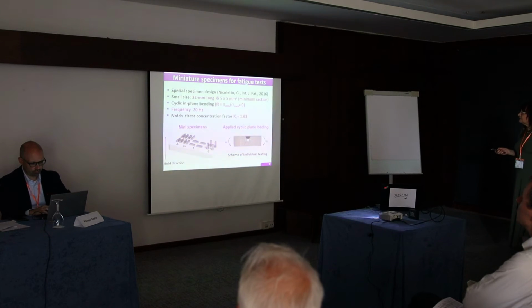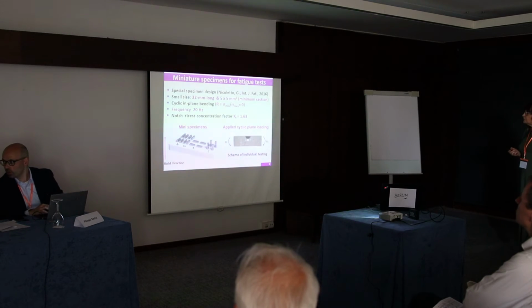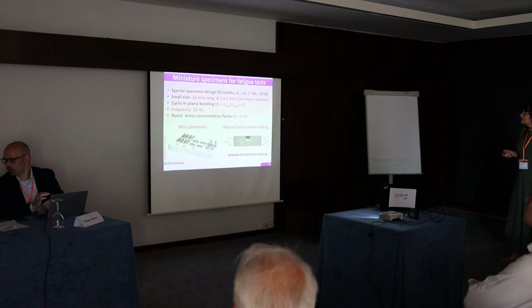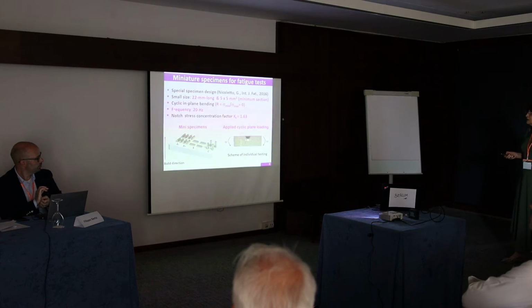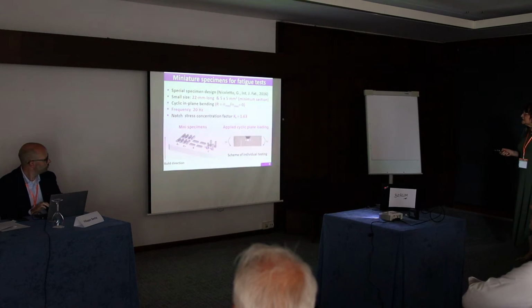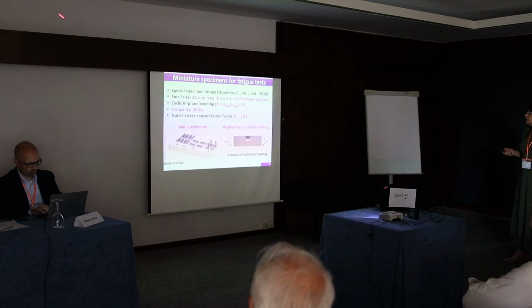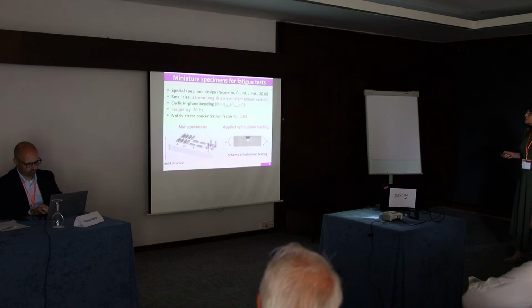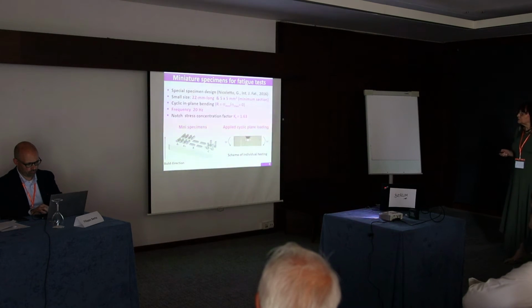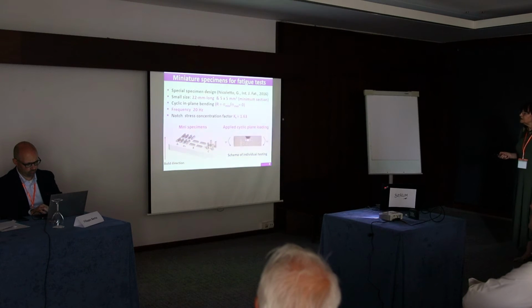Here we can see miniature specimens for fatigue tests. This is a special specimen design prepared by Professor Nicoletto from the University of Parma. The specimens are small, so here are the sizes used for specimen production. Cyclic plane bending was used with R ratio equal to 0. Frequency was 20 Hz, and the notch stress concentration factor was KT equal to 1.63.